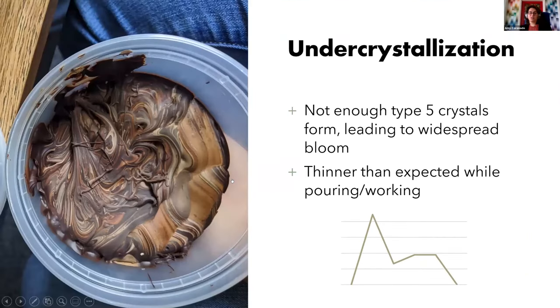So this is under-crystallization. This is the other side of the spectrum. If you don't have enough type 5 crystals forming, you get bloom. This marbling effect you see in the photo is difficult or impossible to see while you're tempering. But what you can see while you're tempering is that your chocolate will be thinner than expected, more watery, if it's not normally very thin. And then when you do the dip test that I was talking about, your chocolate won't solidify in the 1 to 5 minutes that you're expecting.